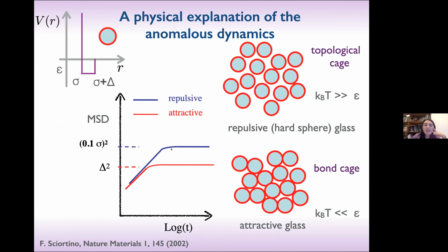I told you in the beginning that for the repulsive glass, for the hard sphere, you have a localization length of the mean-square displacement in the glass that is roughly 10% of sigma. And so you have this topological cage, and you are at a thermal energy that is much greater than the attraction energy. If you go in the opposite limit, you are stabilizing the bond cage. You are at very low temperature with respect to the energy, and you are in this attractive glass. And in this attractive glass, particles are close to each other, and they are basically stabilized by the bonds.